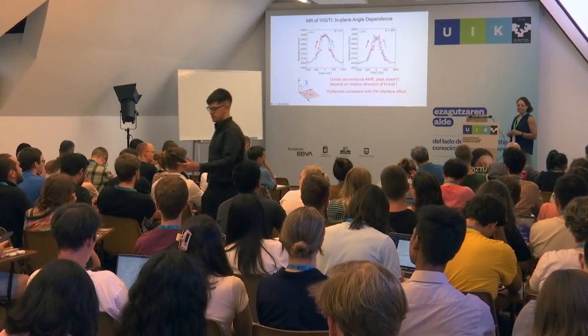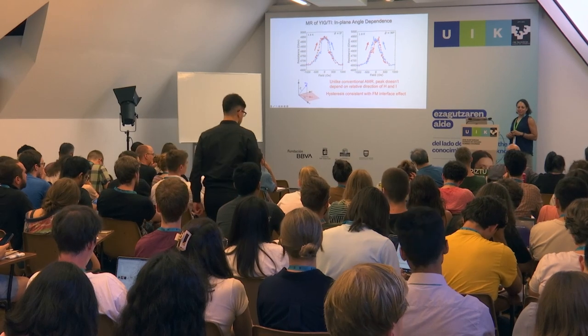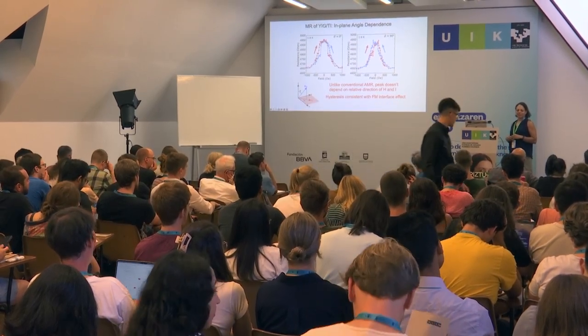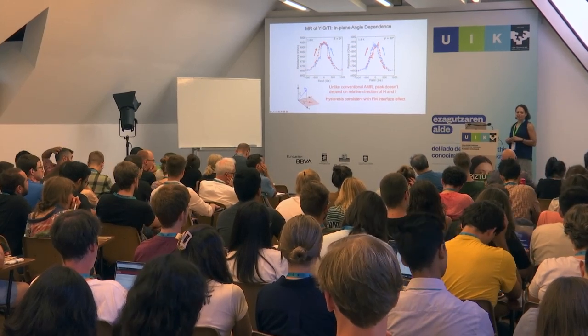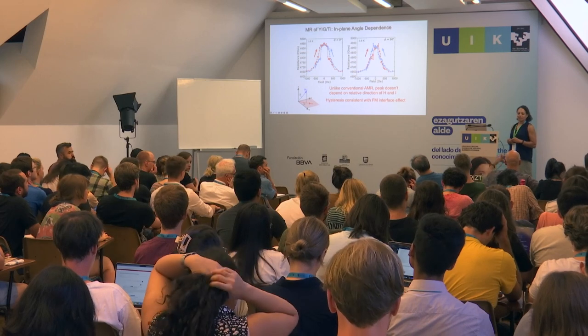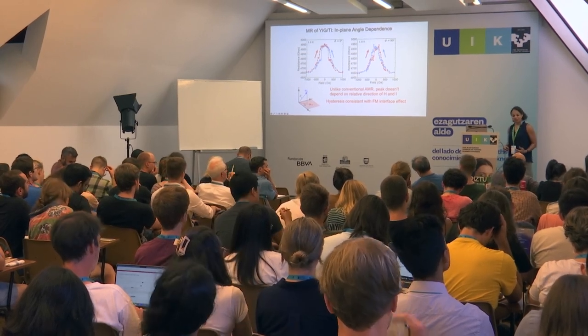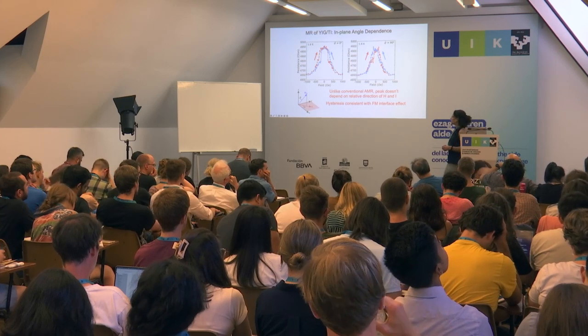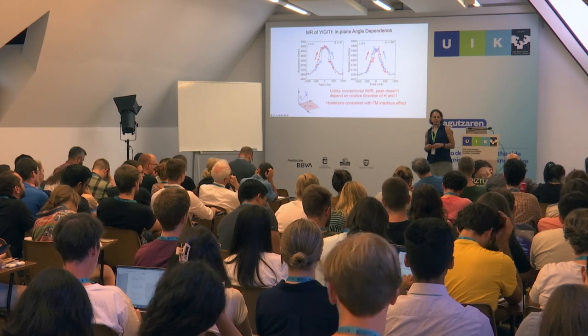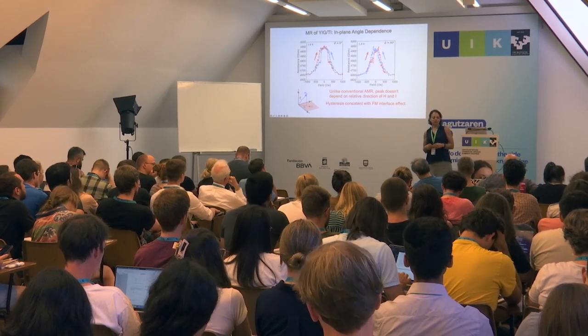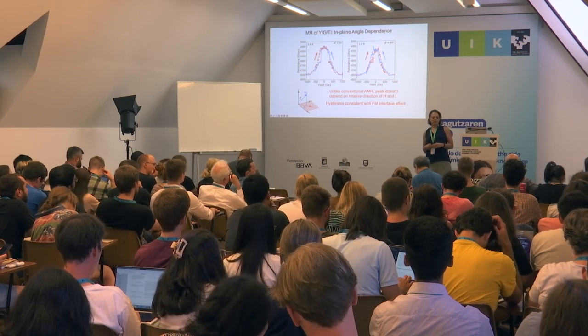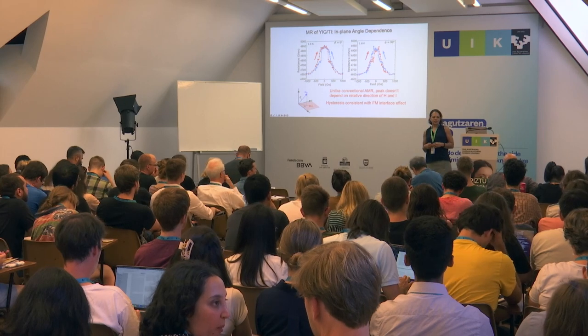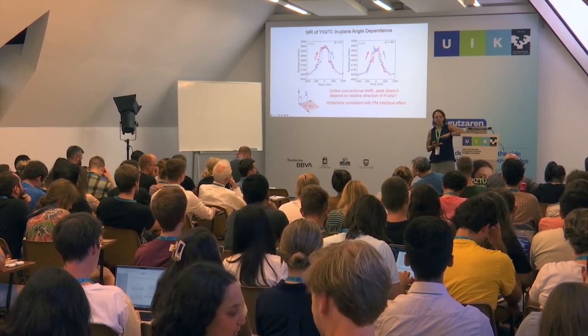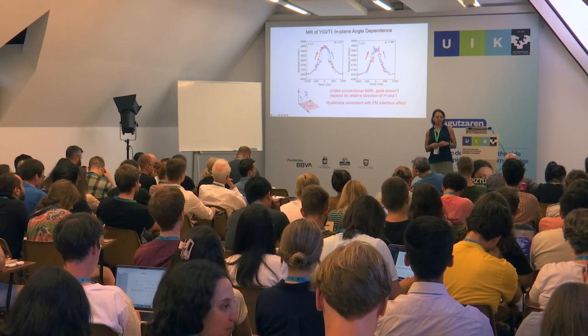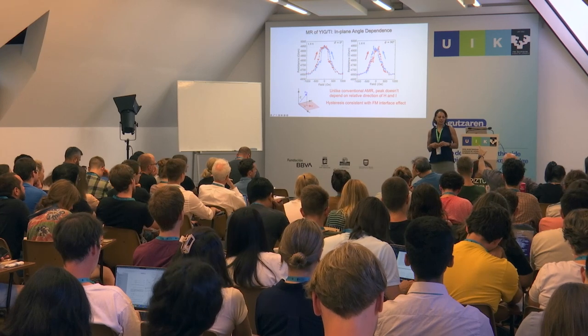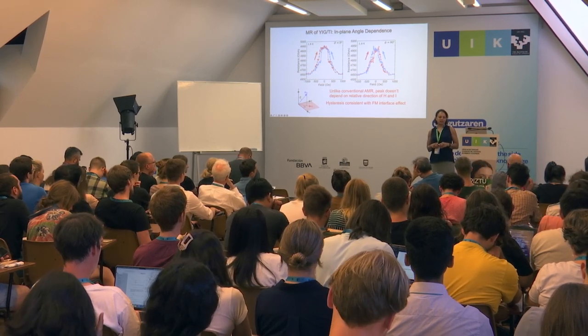One would measure just the hysteretic curve with YIG with the topological insulator film. And if that widens the hysteresis, you know that something is basically happening. But YIG is an insulator, right? To see whether it changes the magnetic field or not. But when you put the topological film on top, it's already coupled at that point, right? Sure. This way you will see whether this transport magnetic field scale corresponds to the hysteresis loop magnetic field scale.